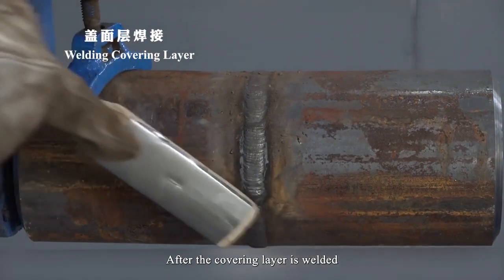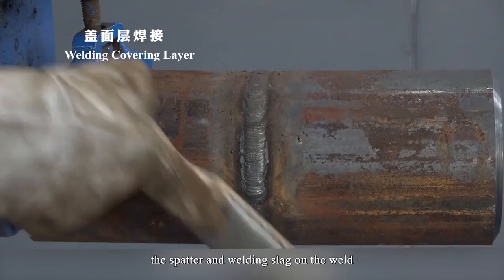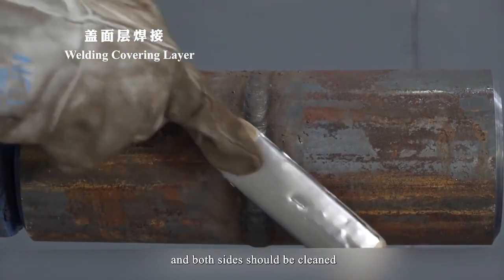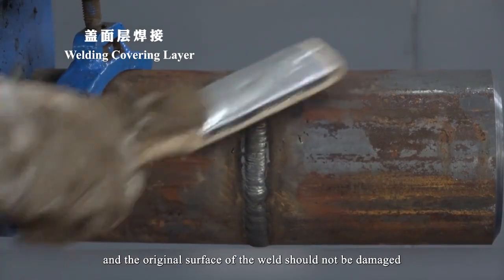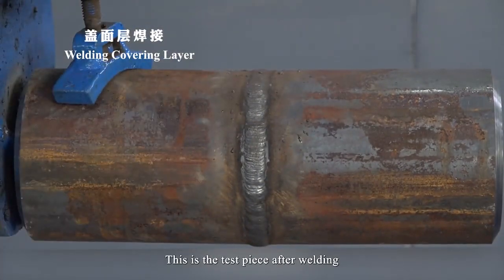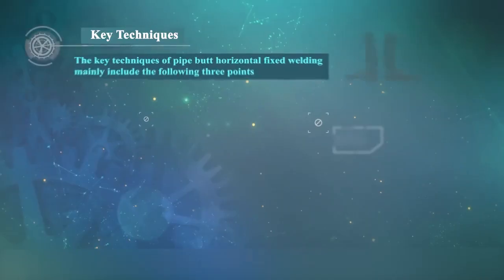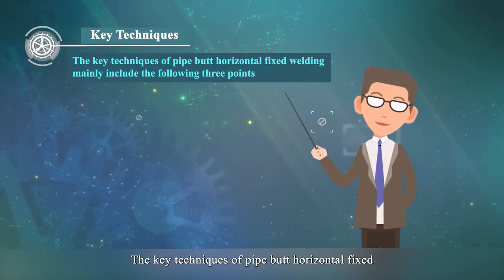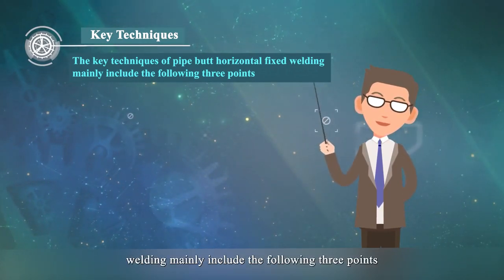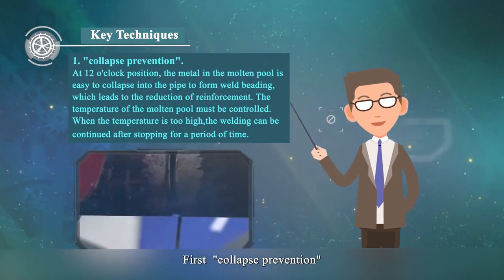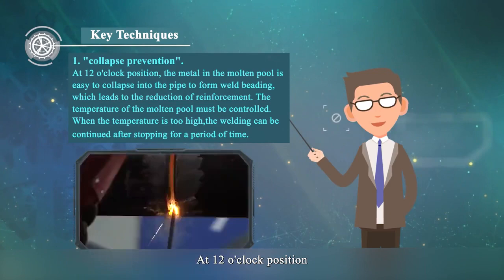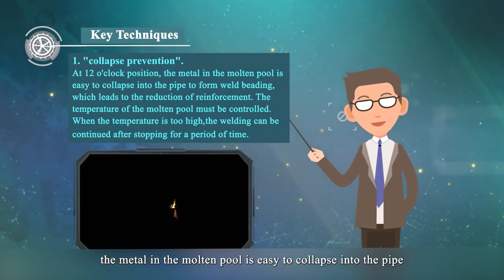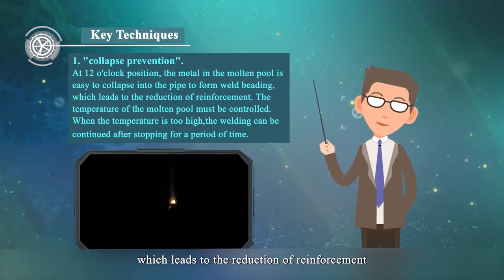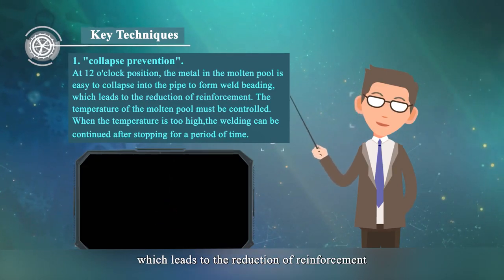After the covering layer is welded, the spatter and the welding slag on the weld and both sides should be cleaned. The original surface of the weld should not be damaged. This is the test piece after welding. Then the key technique of pipe butt horizontal fixed welding mainly includes the following 3 points. First, collapse prevention. At 12 o'clock position, the metal in the molten pool is easy to collapse into the pipe to form weld beads, which leads to the reduction of reinforcement. The temperature of the molten pool must be controlled.